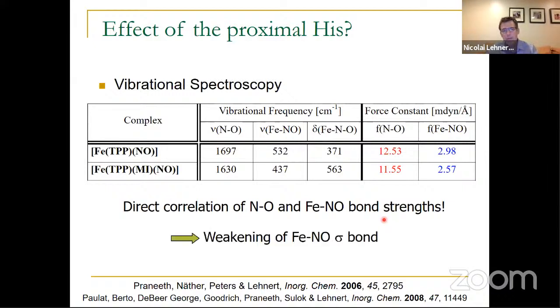So what that means is then that the electronic effect that we're looking at for the activation of soluble guanylate cyclase is an effect that comes from the Fe-NO sigma bond. And that gives rise to this direct correlation that we observe in the vibrational data. So we can deduce that. So we can look directly at the electronic effect that's responsible for this trans effect.